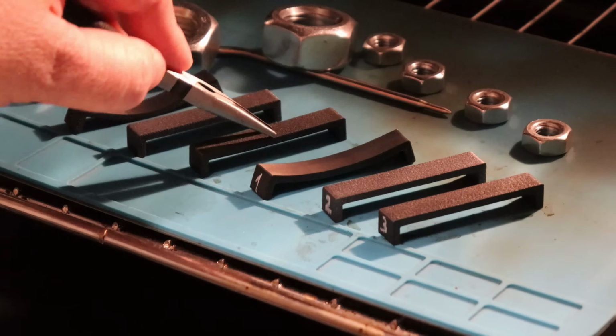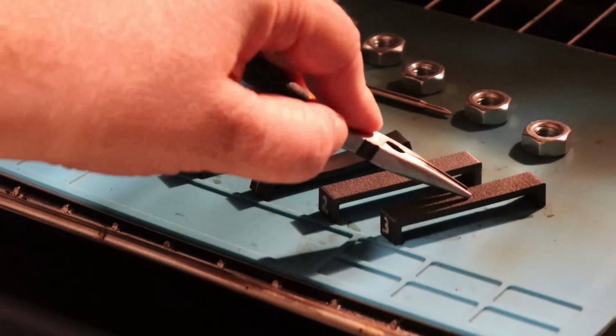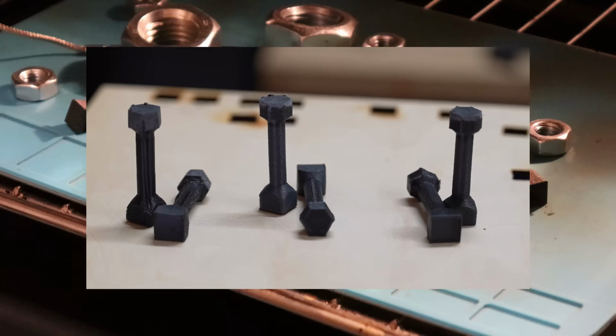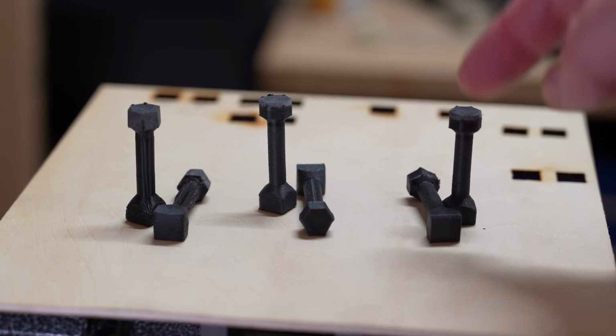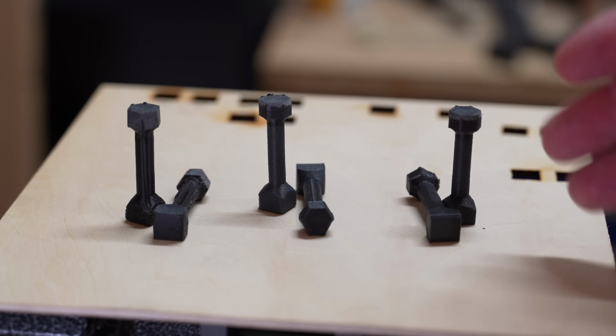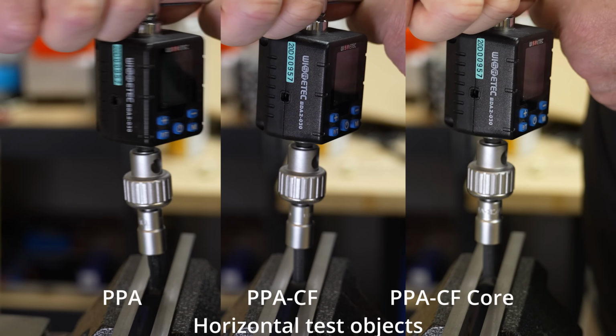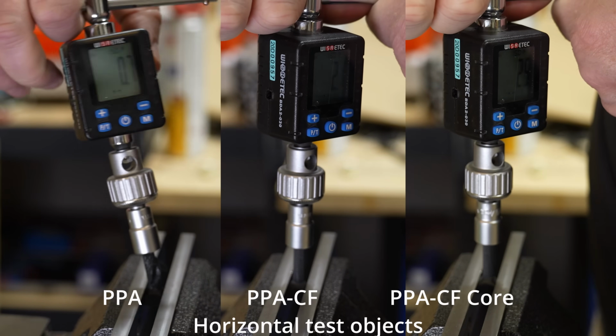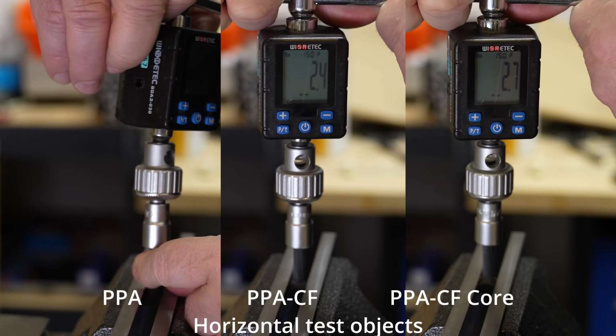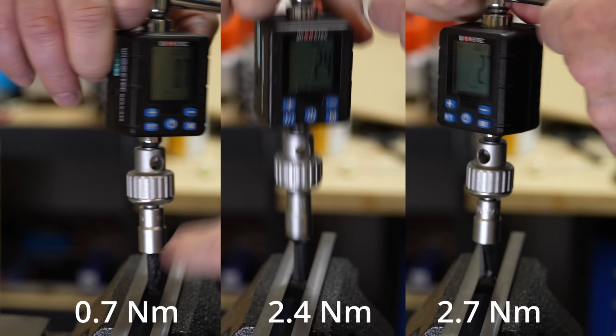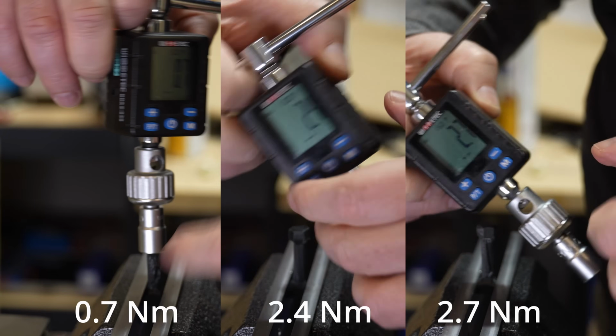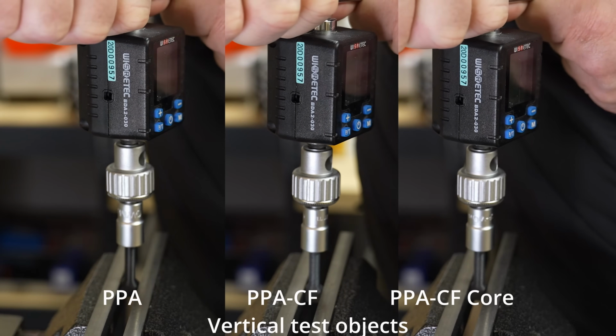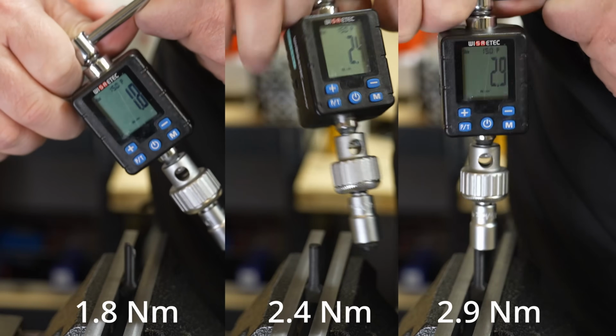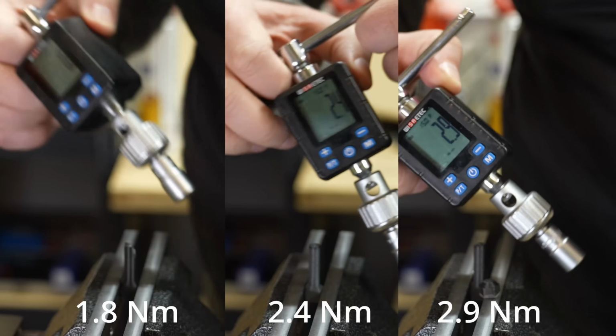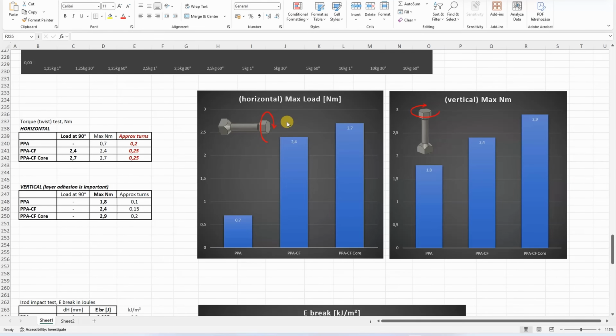And they are still perfectly hard. The torque or twist test with horizontally and vertically printed test objects, and here I don't have annealed versions. Horizontal test objects: PPA broke quite early, 0.7. 2.4. 2.7. Vertical test objects with the same dimensions: 1.8, 2.4, 2.9. I saw this so many times.